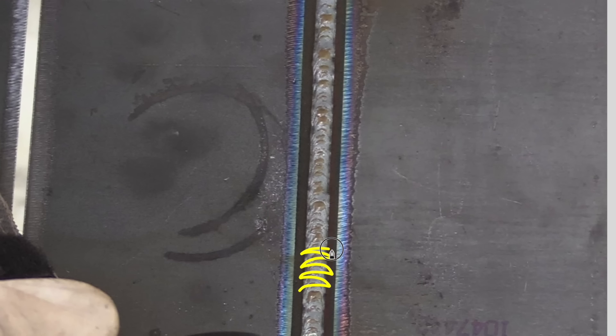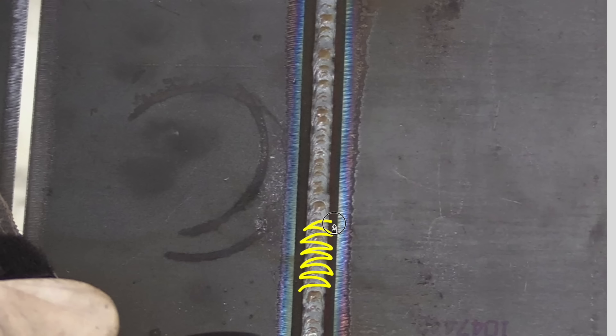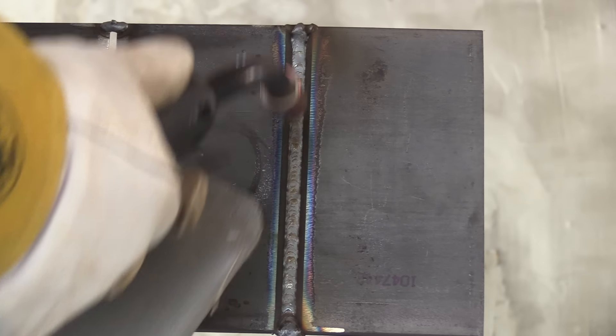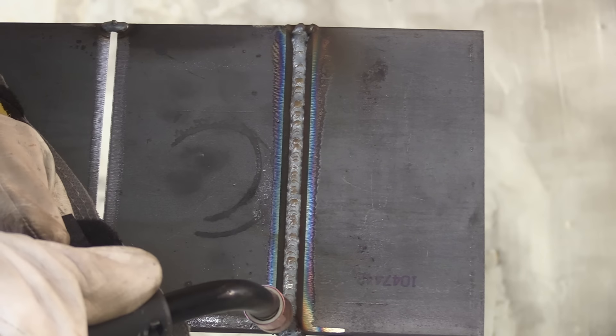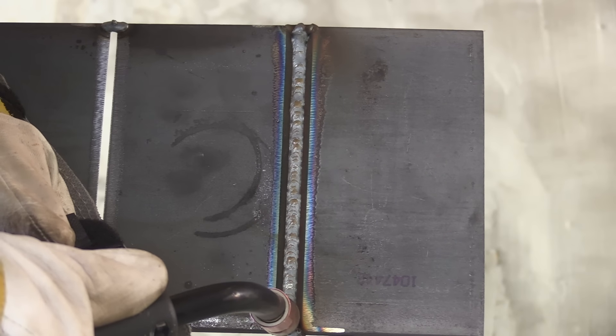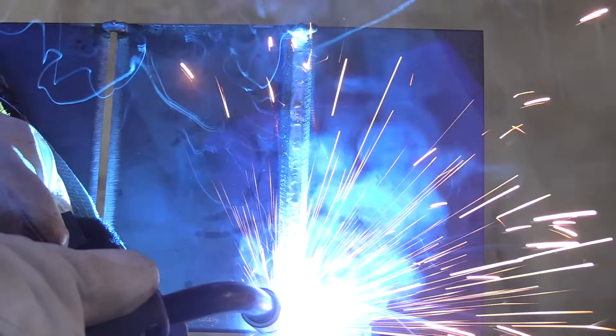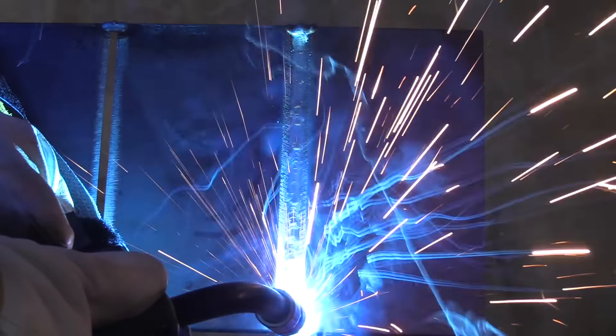This is the motion that you're going to see on that second pass. And I'm going to stop short of consuming that edge. I want to leave about a sixteenth there. And I want this thing to be about a sixteenth below flush for the cover pass. That's about ideal when you can do that.